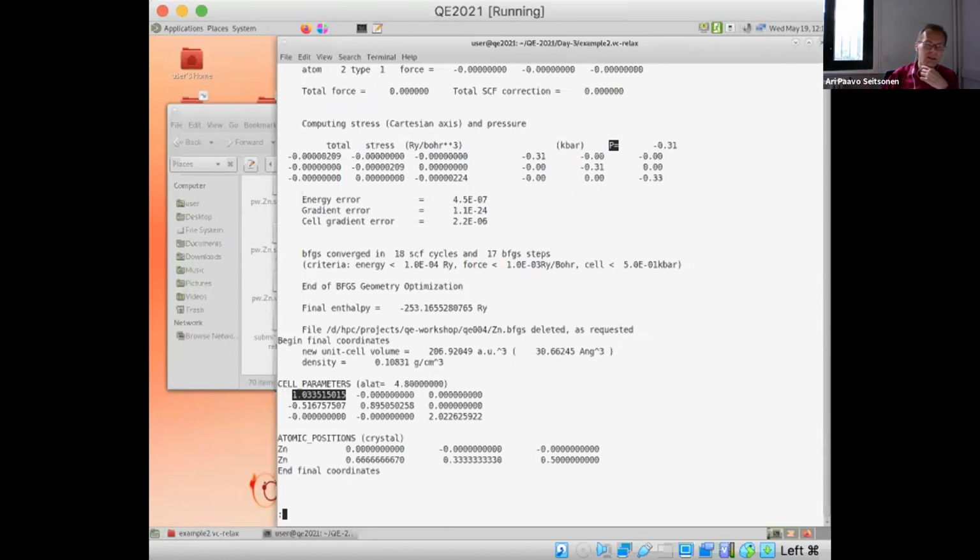And the main part of that is due to the exchange correlation. It could be that the experiments are also at finite temperature. If you are lucky, you find values which have been extrapolated to 0K. And then there are the nuclear quantum effects, zero-point effects, and so on. But I would say normally you will have 1-2% too large lattice constants if you use the GGA in normal materials, not the van der Waals cases and so on. So these are the final values, and this is the final result from the calculation.